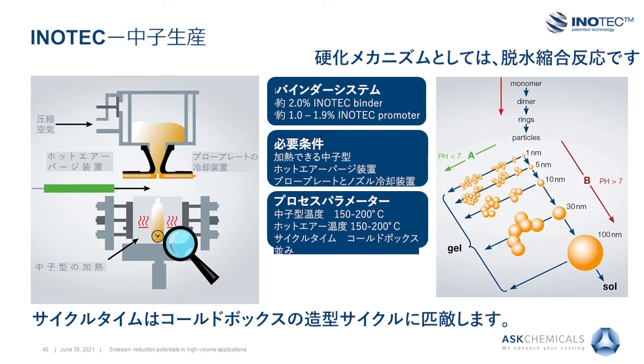A typical molding mixture based on silica new sand is composed of approximately 2% of the liquid INOTEC binder and 1.0 to 1.9% of the solid INOTEC promoter. The higher the addition rate of the promoter, the higher the performance level of the product. The resulting molding mixture is fluidized by compressed air and transported to the cavity of the core box via a cooled shooting plate with integrated shooting nozzles. High diameters of the shooting nozzles and temperature control of the shooting plate are fundamental to assure high productivity in the production and sand cores of high quality.